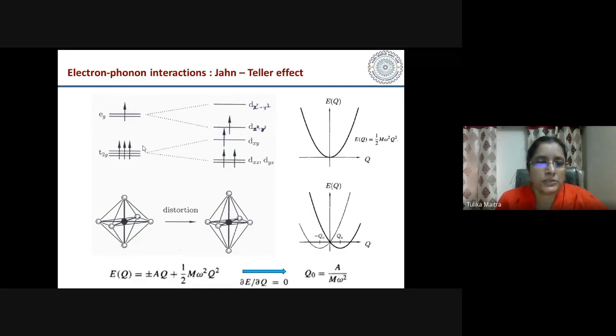And also another effect that is often seen is called the Jahn-Teller effect. So when you have situations where we have fewer electrons than the available orbitals, which is shown here, we have one electron in the doubly degenerate eg orbital. Here what happens is that it can be shown that energy is reduced when the crystal undergoes a distortion and one orbital becomes lower in energy and this electron goes there. So it can be shown that energetically this state is lower in energy. This is called the Jahn-Teller effect. This kind of splitting you can also evaluate, and you can compare it with that of the crystal field splitting. So these energy scales one can determine from the DFT calculations.